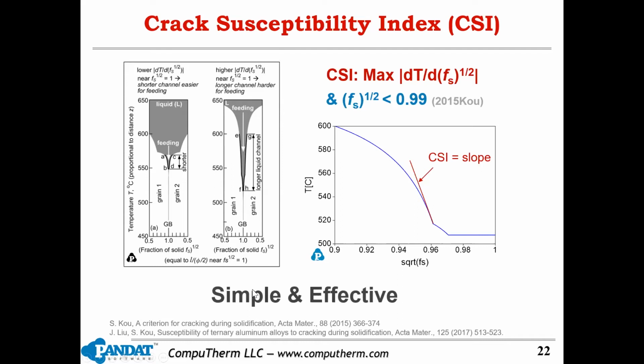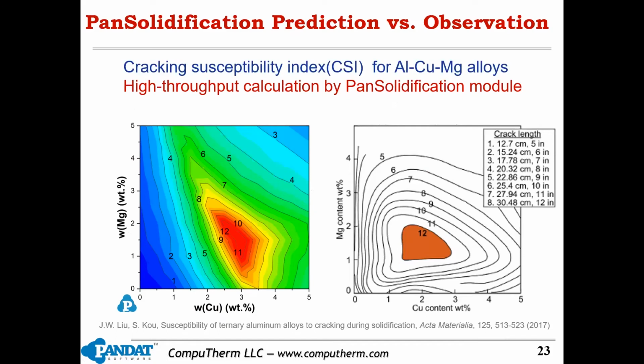Okay, so this index is very simple and effective. In here, I just want to use this criterion. We can calculate the CSI given any alloy composition. In this example, we use high throughput calculation to calculate the CSI for several hundreds of alloy compositions in this ternary system, aluminum, copper, and magnesium in the aluminum corner. Copper varies from 0 to 5%, and magnesium also varies from 0 to 5%.